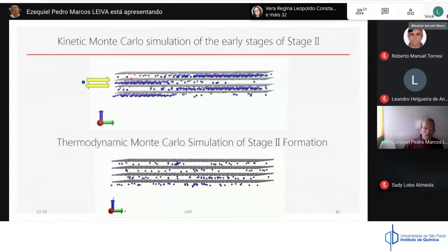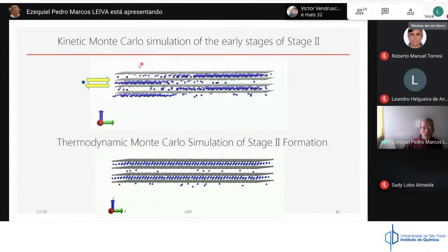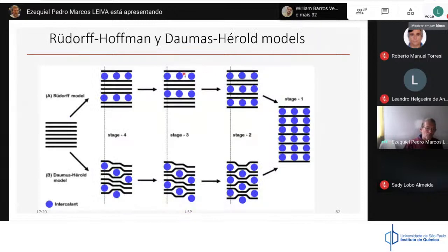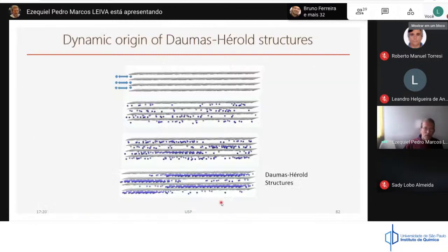If you compare the kinetic simulation with the ordinary Monte Carlo simulation, you will find a number of defects. And these defects were addressed a long time ago in the literature. There are two models to describe the filling of a graphite lattice with ions. One is the Rüdorff model, which shows a very ordered system, and the other is the Daumas-Hérold model, which shows a number of defects. So we started to consider this system, and we could find out the origin of this defective structure.